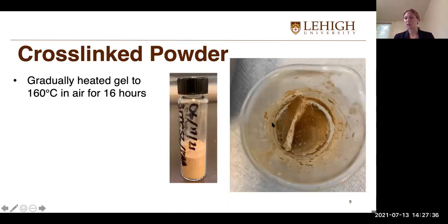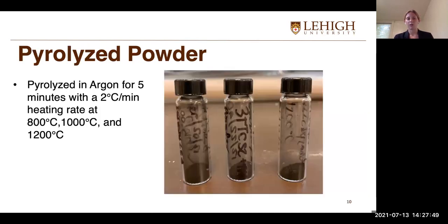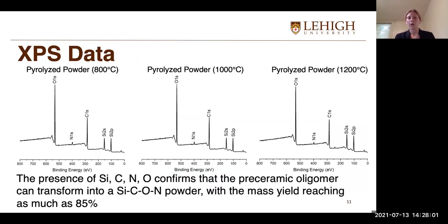I then cross-linked this and crushed it into a powder. To cross-link it, I gradually heated it to 160 degrees Celsius, and then that sat in air for 16 hours in the oven. And I was then able to pyrolyze the powder at 3 different temperatures. So I pyrolyzed it at 800, 1000, and 1200 for 5 minutes with a 2 degrees Celsius per minute heating rate. And from there, I was able to perform some characterizations.